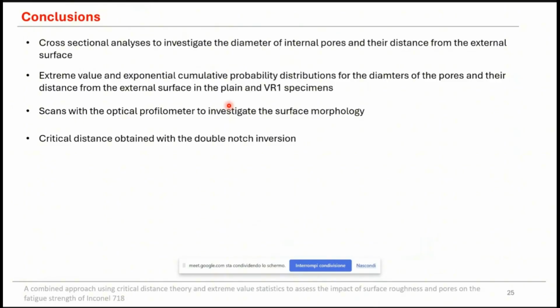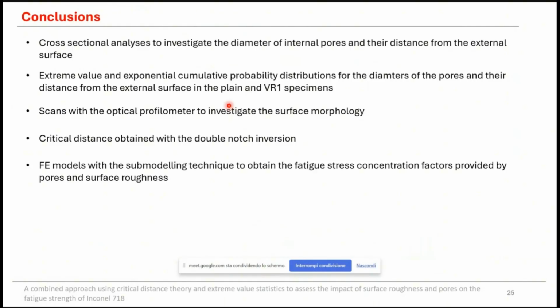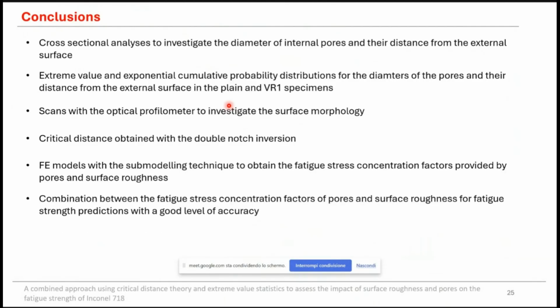Then we moved to the identification of the critical distance through the double notch inversion, and we calculated the fatigue stress concentration factors provided by pores and surface roughness once finite element simulations were completed. Then we combined the two effects in a simplified way by multiplying the fatigue stress concentration factors at 90% of probability. We obtained a higher prediction accuracy with the line method than with the point method.